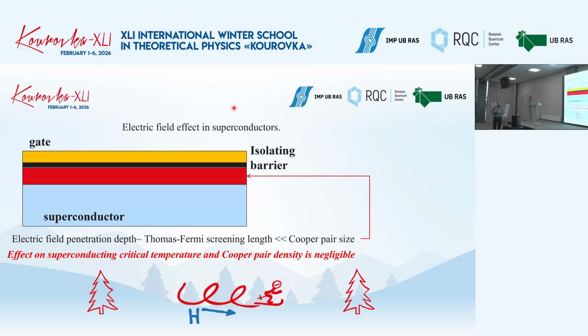And now, the electric field effect in superconductors. What should we do? We need to just take, for instance, this blue superconductor, a superconducting film. Then put an insulating barrier and the gate. Then we apply the gate voltage, and we want to control, for instance, the critical temperature. This is a very bad idea. Why? Because, of course, this blue guy is a superconductor, but it's a metal. And this is why the static electric field is screened in a metal at a very short length, which is basically the Thomas-Fermi screening length, a few angstroms.